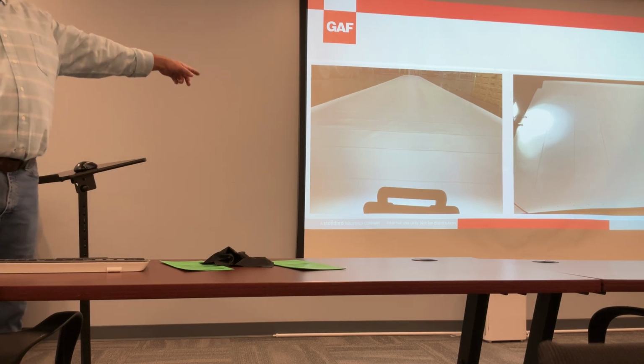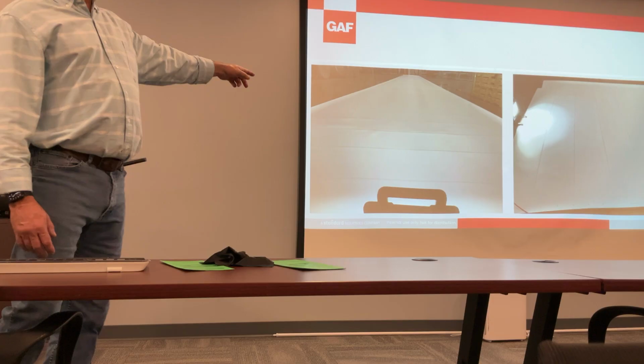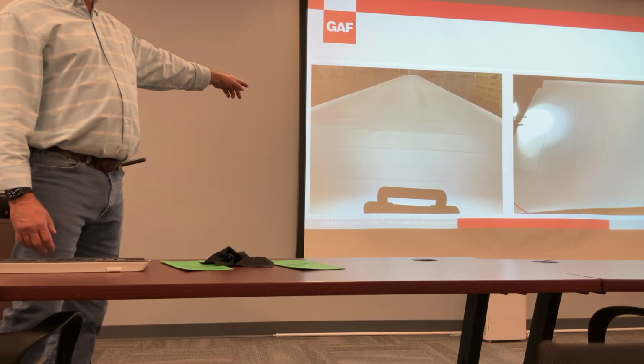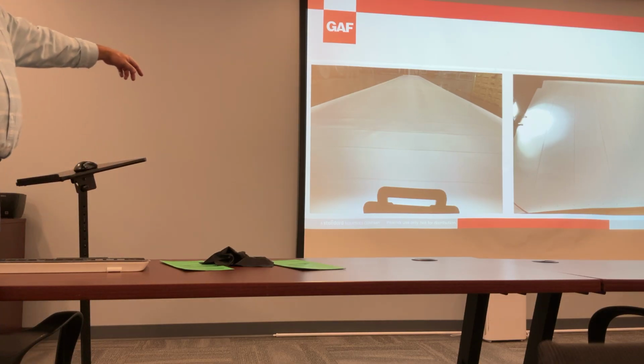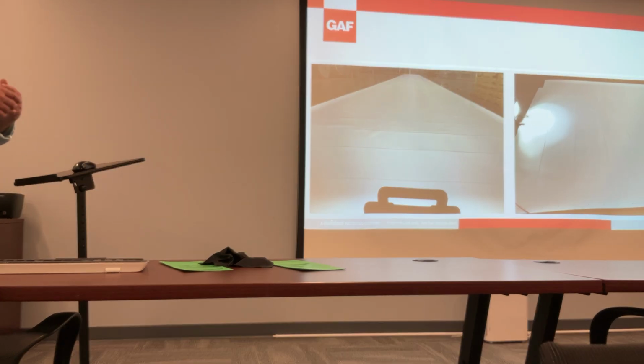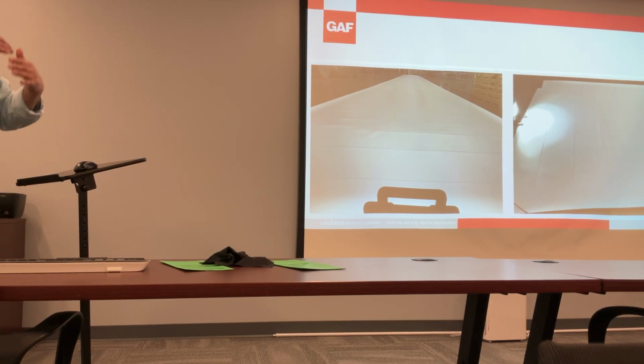Okay, so that's in every sheet we make. It can be a lot worse. It's just not as pronounced as this, right? So that happens at the winder, when you get that first wrap and then you get the second wrap, there's an offset. And as it keeps on going, it's gonna keep putting that line in the same spot because of that offset. You've got that thicker part, and then you're dropping down to the core that's a little bit thinner, from where I'm rolling over myself. So that little spot is a little stretch. It's the teeniest, tiniest stretch.